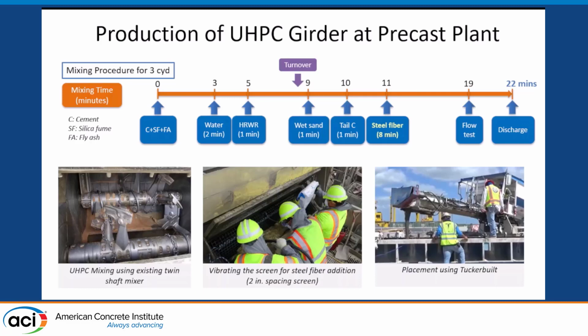As we get started, we're doing a dry mix of cement, silica fume, and fly ash. That's mixed for about 3 minutes, and then we move to the water addition for 2 minutes of mixing, followed by HRWR. After a total of about 9 minutes, we started to see the turnover of the mix, similar to what we saw in the lab. Then you'll see that we're adding the wet sand. There were some adjustments made because of the addition of wet sand from the plant, and we found that adding it at this stage, after the paste had combined, worked well.